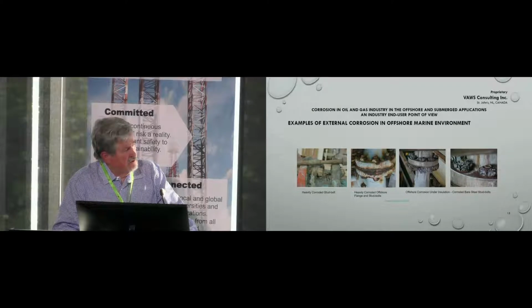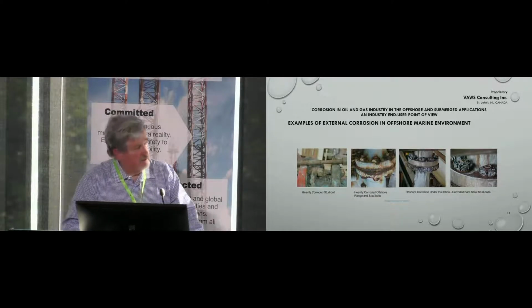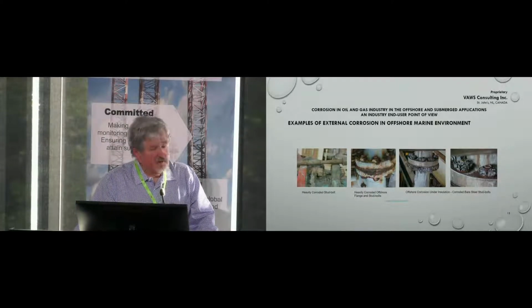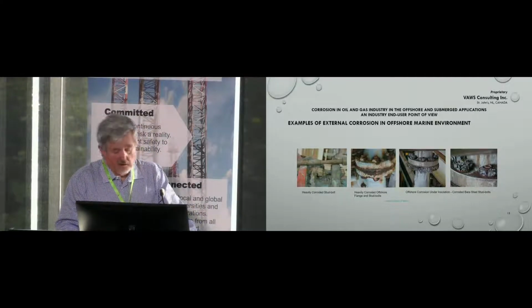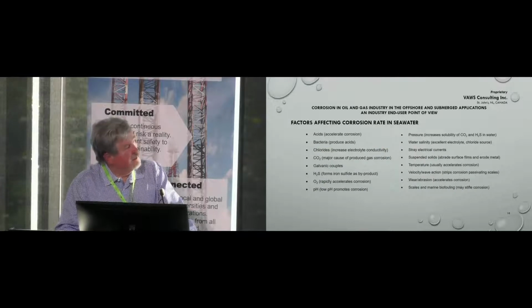The two pictures on the right side, and actually the third one too, this is caused by insulation. When you have a wet environment rich in chlorides, you can see that these bolts don't look like bolts anymore. And they probably don't have the strength they actually should have. And you don't see it because you have thermal insulation around it. And so inspection and knowing these things is very important before you get into trouble real quickly.